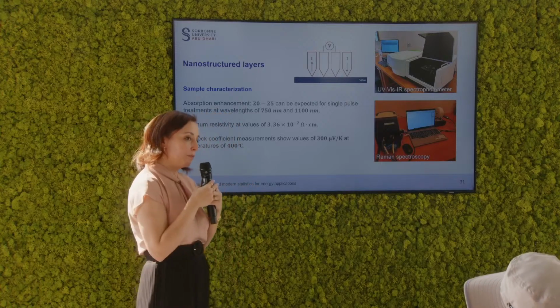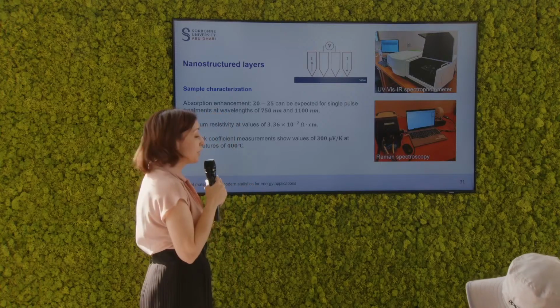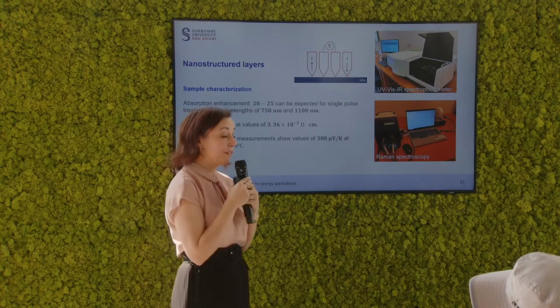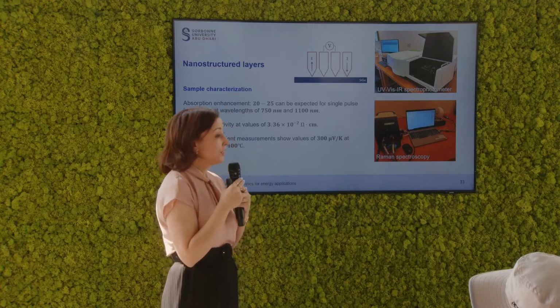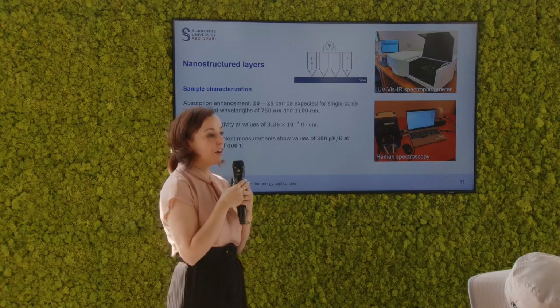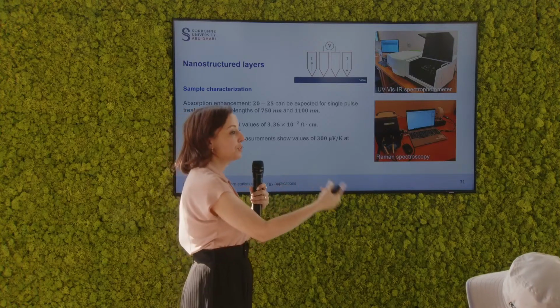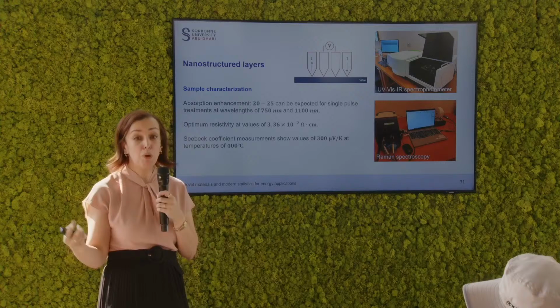And the optimum resistivity values for our case for a single pulse laser treatment is around 3.36 milliohm centimeter. This is just merely an indication that you have a conductive layer. So instead of the amorphous layer that you started with, now you have a polycrystalline layer.